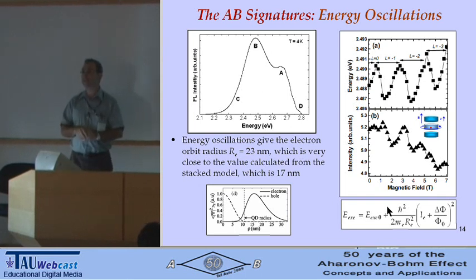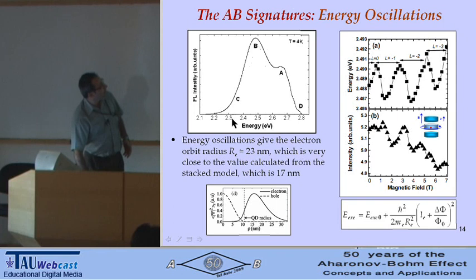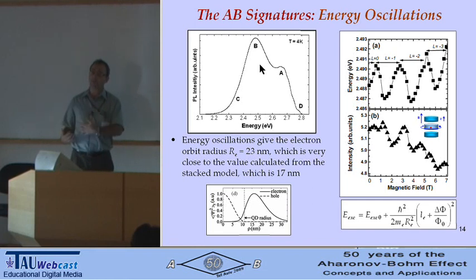I wonder whether you see any correlation in the width of the Gaussians that you fit to get the energies and intensities. Do they also oscillate with the flux? The width of the Gaussian peaks, I didn't check that. We just fit and get the peak position. But the width, it's a complicated system because we have isoelectronic bound excitons there. To give you the full flavor of this, I would have to go into the specifics of the system. There are probably quantum dots here, but this could be isoelectronic bound excitons. We really can't pinpoint the exact transition from isoelectronic bound excitons to quantum dots. And they do oscillate too.